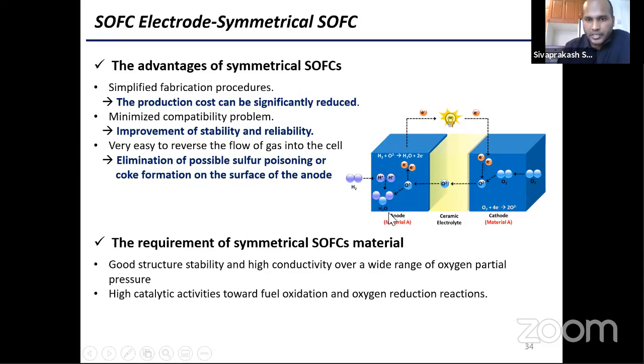For example, material A is used as the anode, and the same material A is used as the cathode. When we start purging with hydrogen or hydrocarbon as fuel, even though carbon is deposited on one side, we can switch the fuel from the anode compartment to the cathode compartment, so that the deposited carbon is exposed to the oxygen containing atmosphere. This deposited carbon is then oxidized to carbon dioxide.